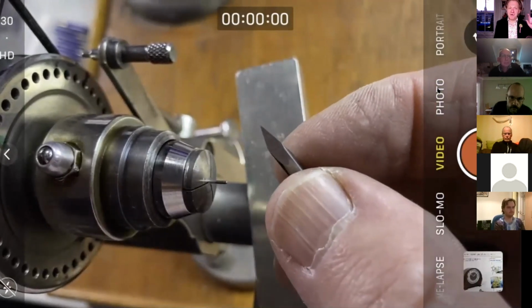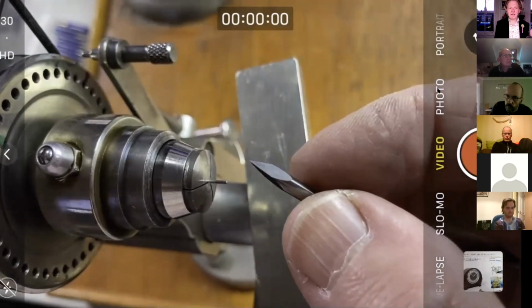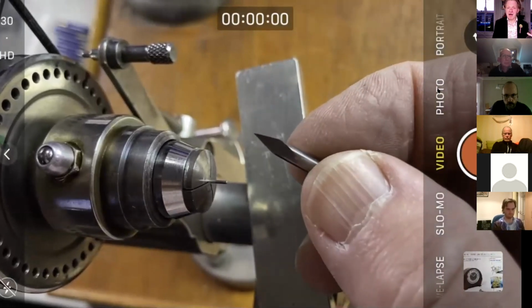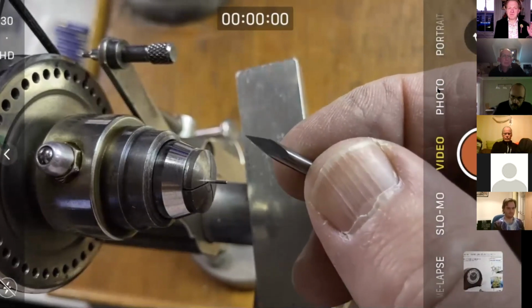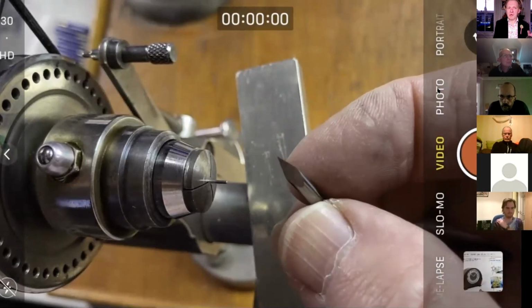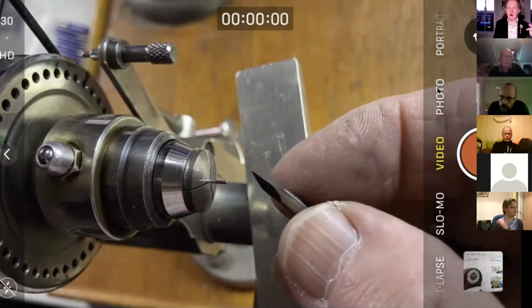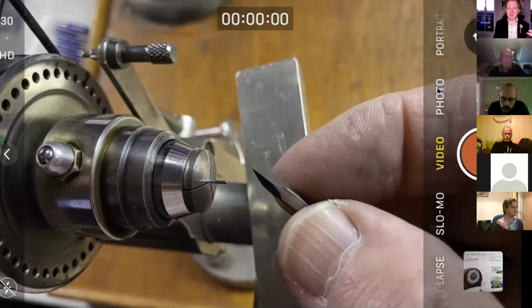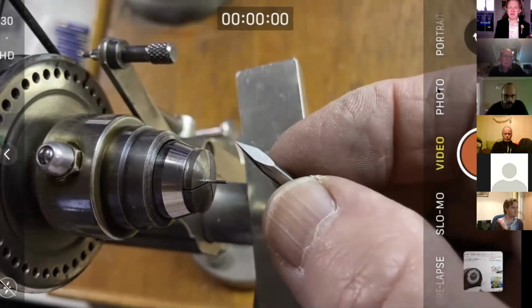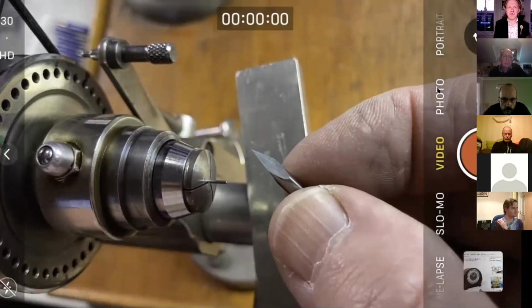And I thought, great, I've got my easy lap diamond things, but it didn't work. The reason it doesn't work might be to do with the quality or the type of carbide that these things are made from. Because the diamond cuts well, of course, it's really hard, but it's kind of brutal. So what happens is that it drags material out of the cutting edge. It doesn't matter how much you grind away, maybe I need finer diamond, you never get a smooth cutting edge. Although saying that, I see that they've managed to do that when they made the thing.